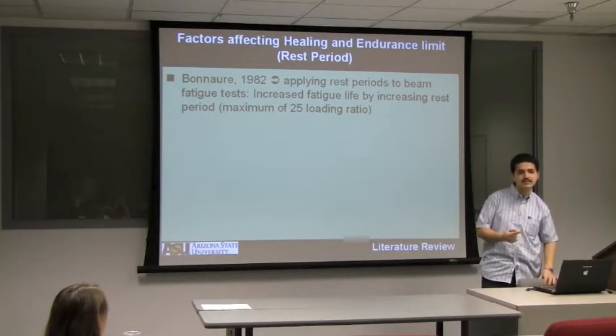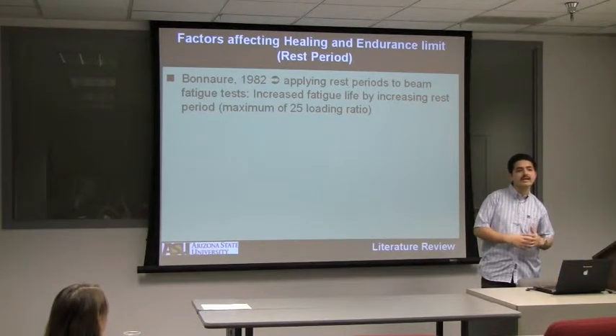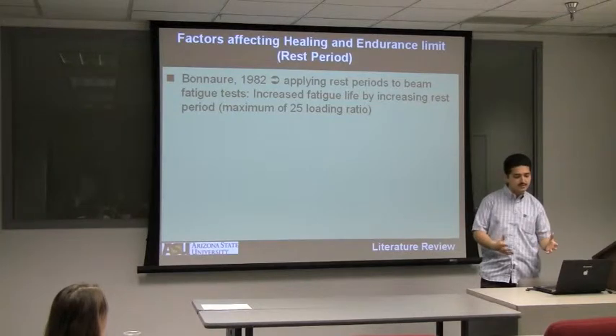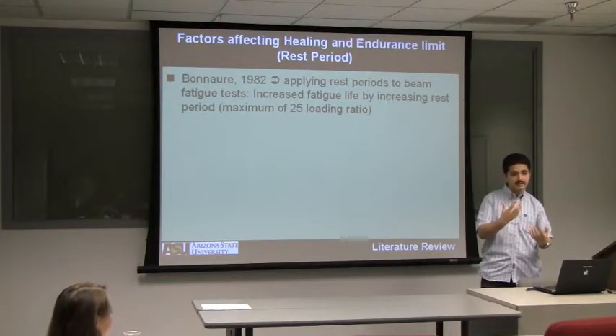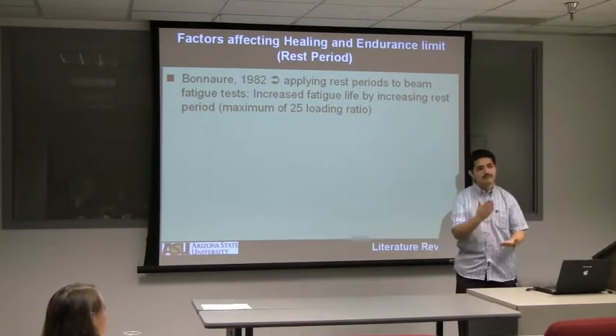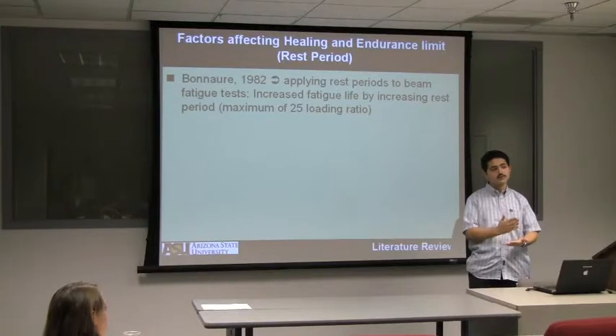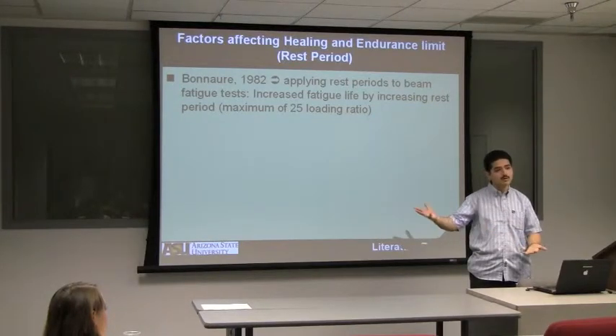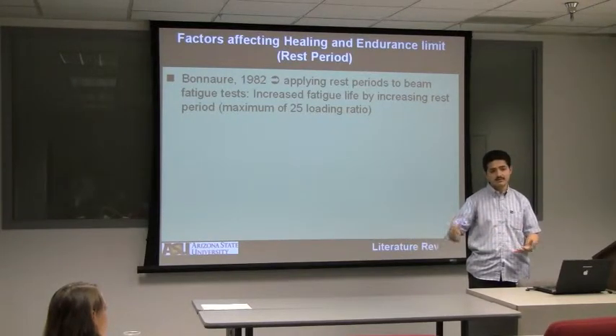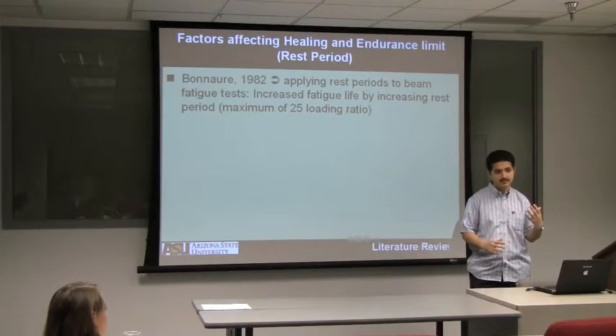So what he mentioned here is that you are not going to gain any more healing if you are applying a very high rest period. He says once you apply a rest period 25 times the loading time, so in my case, loading time 0.1 second times 25, this is equal to 2.5 seconds. So he's telling me that if you have a rest period equal to 2.5 seconds or more, you are not going to gain any more healing. The full healing, as I mentioned earlier, will happen by applying 2.5 seconds.